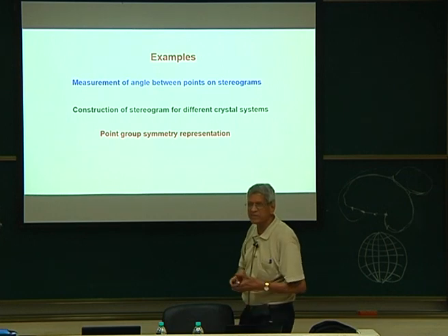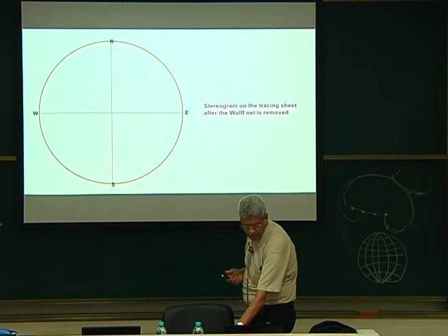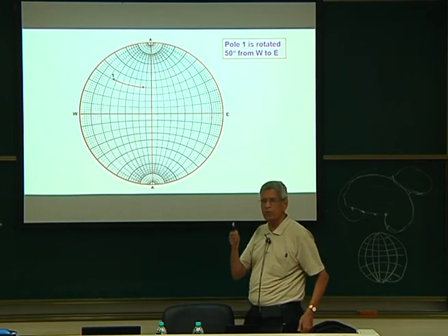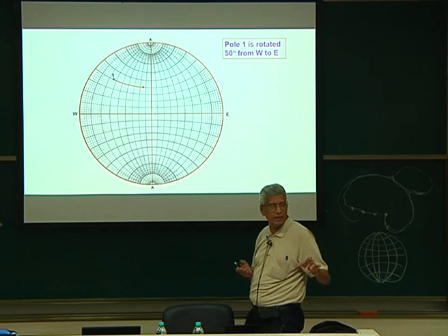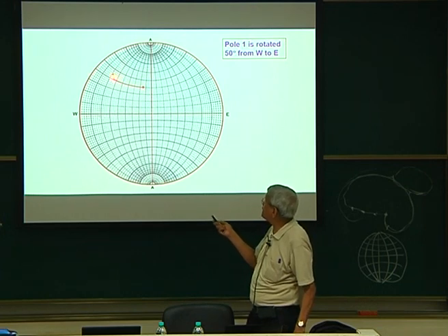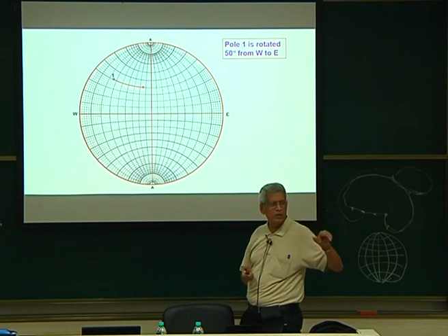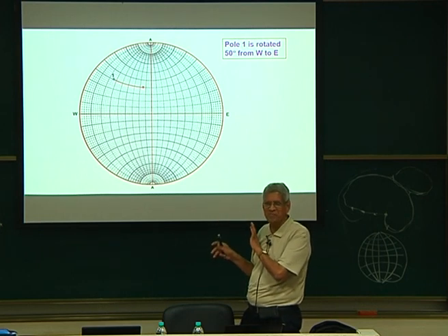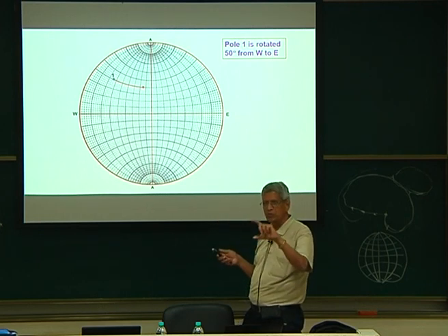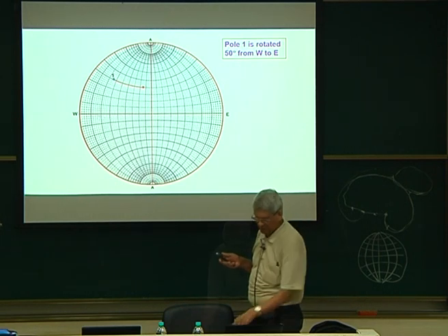There are a lot of exercises on how to measure the angle, but essentially what is important is that when we move from one point to another point, and I want to measure that angle, we have to keep these 2 points either on a latitude or on a longitude, and only then does it give the true angle. That is one of the restrictions imposed. Between any 2 poles where we want to measure the angle, that is the way it has to be done.